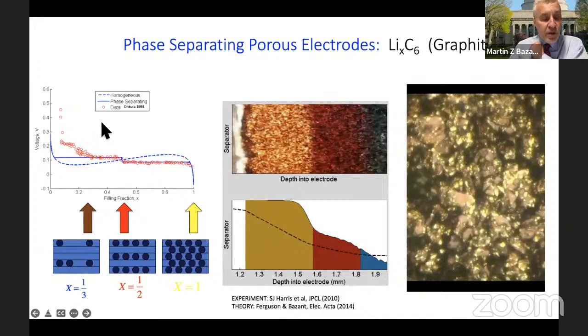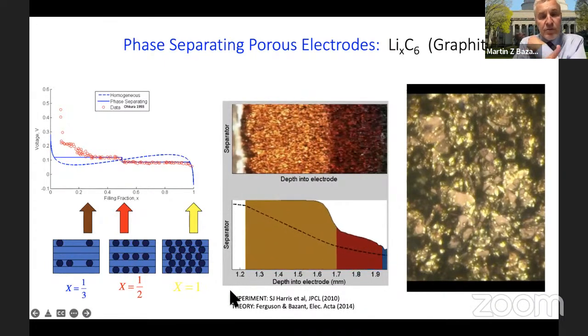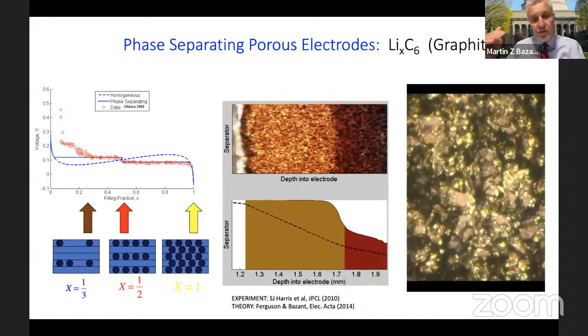Now, a nice property of graphite, which also has been known for a long time, is that these certain special phases have different optical colors. So the full phase is kind of a yellow gold color, half full is red, and then 1/3 full is sort of a brownish color, or even bluish brown, and then empty is sort of a black color. And so, in fact, there were experiments done already more than 10 years ago, taking a graphite anode, unrolling it, and observing lithium going in and out. And you can see on top what the image looks like. And so those are basically different phases of graphite that I just described to you, going from a filling of basically near 0 to 30% to 50% to 100%.